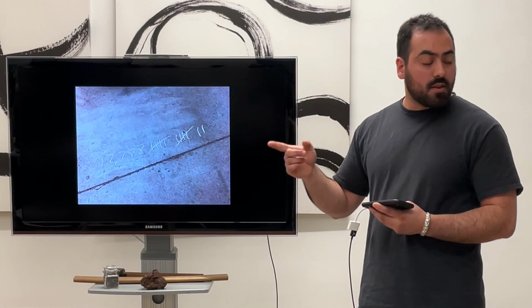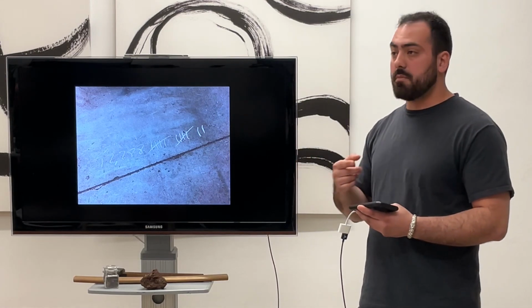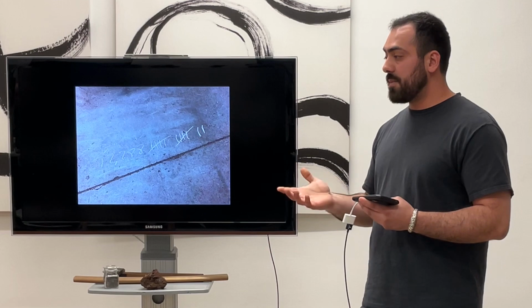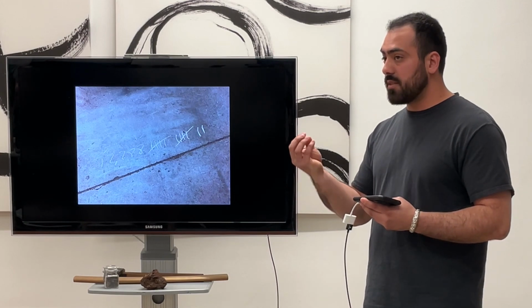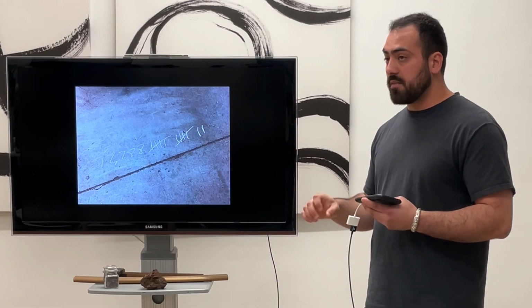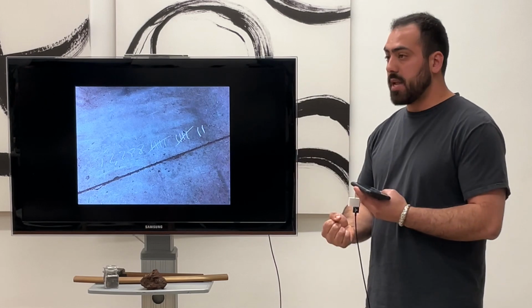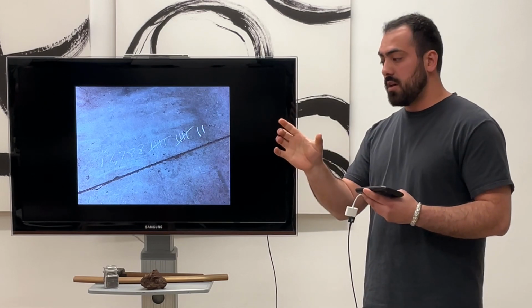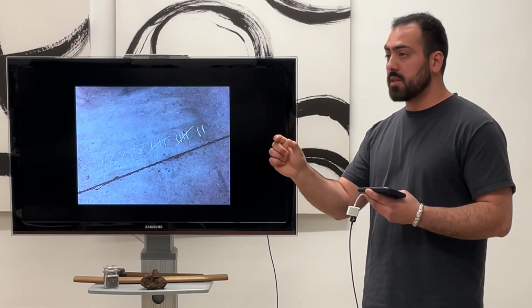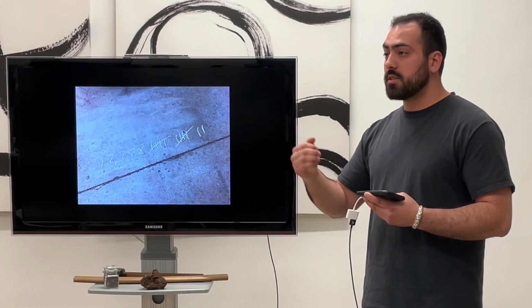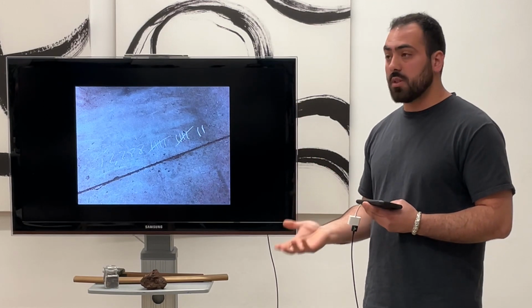Also, the blades that I've made from this mono steel construction, I had a piece that failed pretty majorly, that had a big bubble in it, and I got kind of upset, and I took it and bent it, and it bent to the point where the nakago and the tip nearly touched before it cracked anywhere. So this material is really resilient. You can do a lot to it.